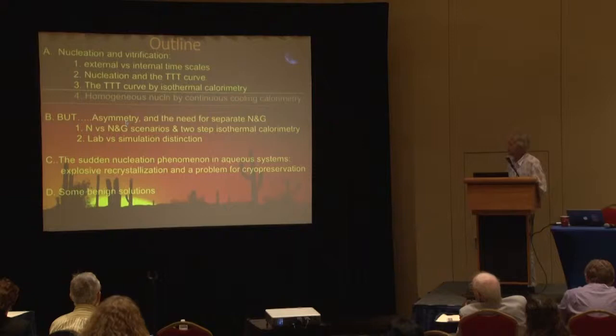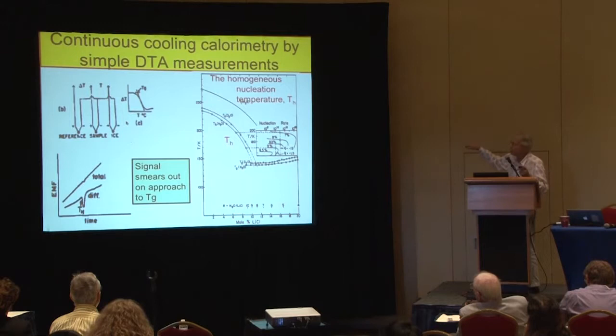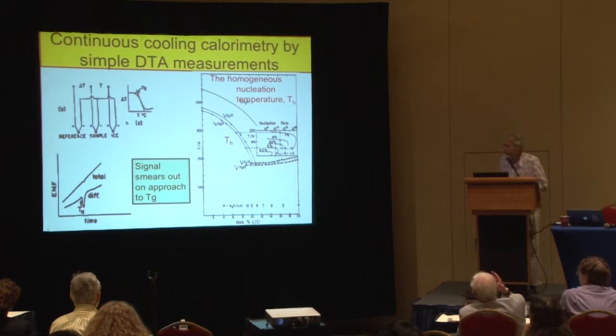Then that's all very well. So we got these TTT curves for a lot of different systems. And now we want to talk about homogeneous nucleation measured by continuous cooling, which requires just a different sort of apparatus. They were done with differential scanning calorimetry. This is done with a much more primitive system, DTA, but quite nice because you can use very corrosive samples without worrying about having to replace your DSC head. And you get a nice signal when the ice crystallizes.